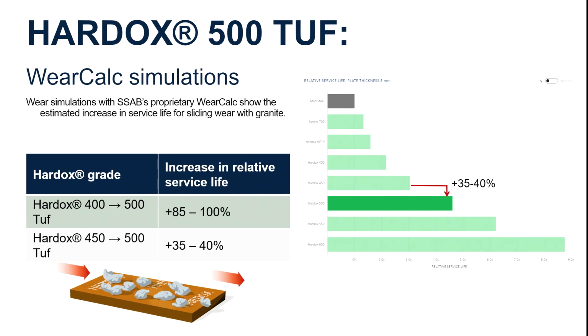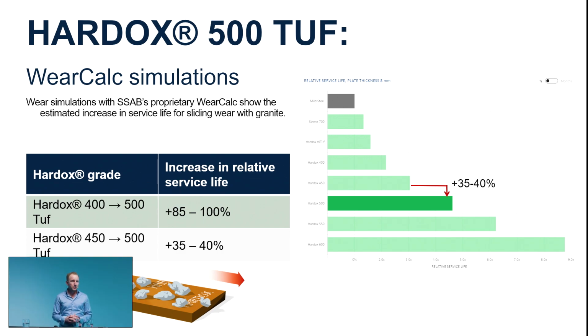If we look at the wear resistance and compare it to Hardox 400 and 450 Brinell steel, what we see is increased wear resistance, for example, for granite rock, which is quite common in the soil. We can see a 35 to 40% increased service life compared to Hardox 450 or another 450 Brinell steel. If you compare it to a 400 Brinell steel, we can see almost double the service life for granite.